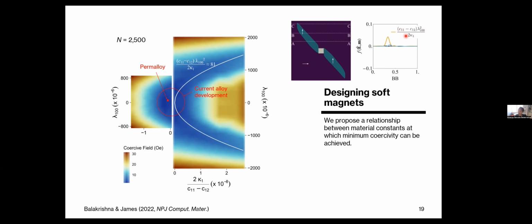And so by minimizing this energy barrier, you can get the soft magnets to rapidly switch from one direction to the other, not just for values where kappa 1 is close to 0, but also for other suitable values. This is one example where we have a quantitative design principle, a mathematical relationship for which you can reduce hysteresis, and potentially a guideline to search for new alloys.